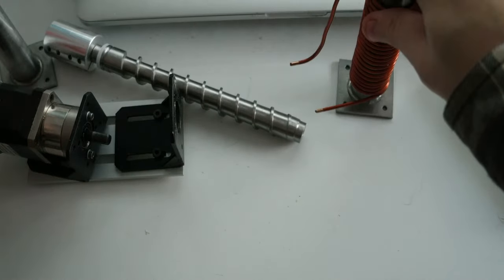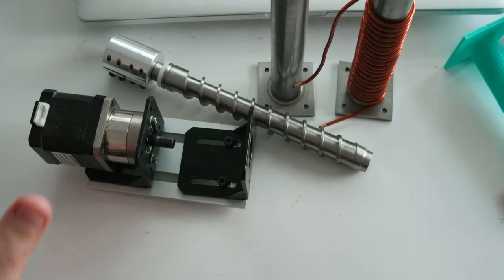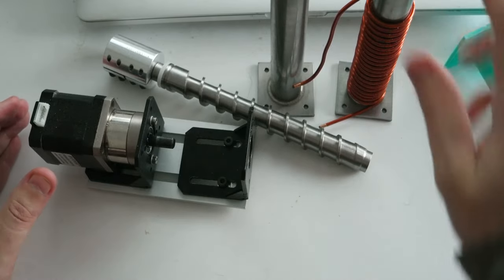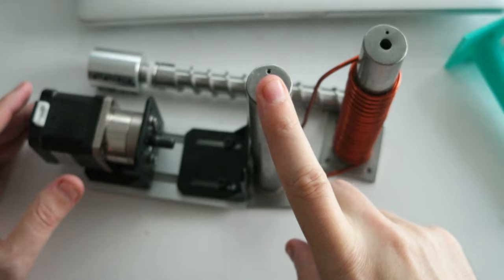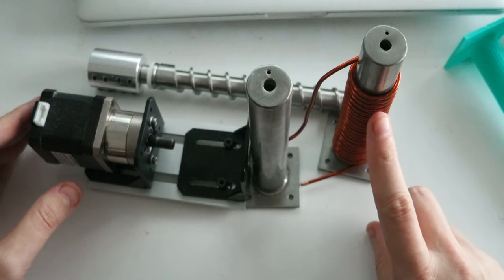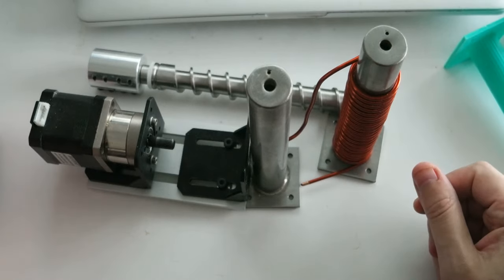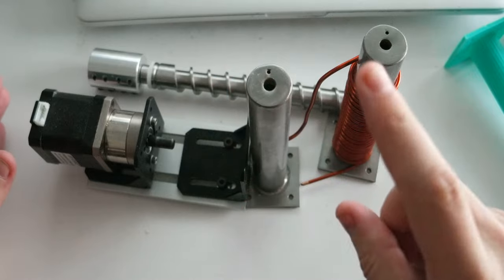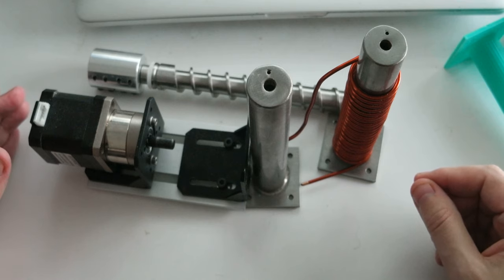So these are the pieces. They are dual extruder because I have the 3D printer, it will be very big, and I'm printing carbon fiber pellets, so I need one for support and one for the carbon fiber pellets. Now I am looking at the carbon fiber pellets, the pellets are longer, about six, seven, or eight, even ten millimeters. So the fiber is much longer than the normal pellets which are two or three millimeters, and that will help me to make stronger pieces.